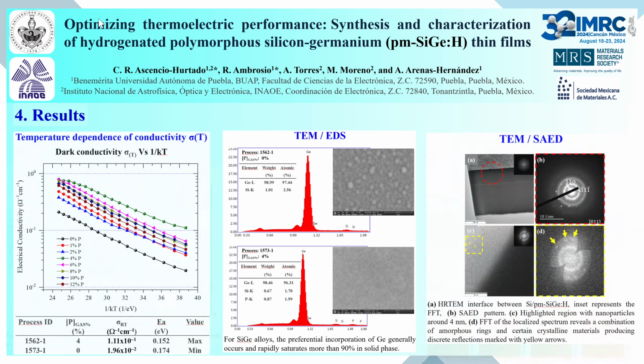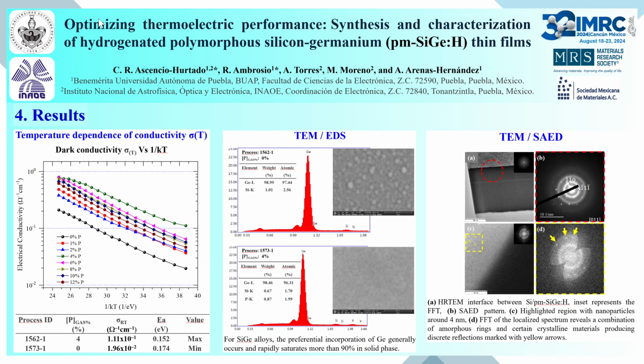The figure on the right shows the high-resolution TEM cross-sectional micrograph of the polymorphous silicon-germanium sample. The configuration of the grown layers is revealed and is visualized better in the selected area electron diffraction pattern. Here, the fast Fourier transform corroborates the amorphous phase.